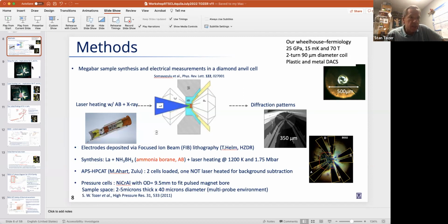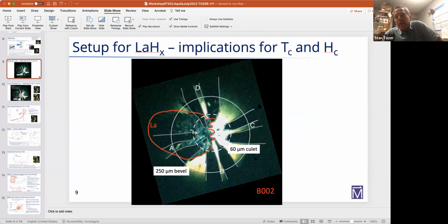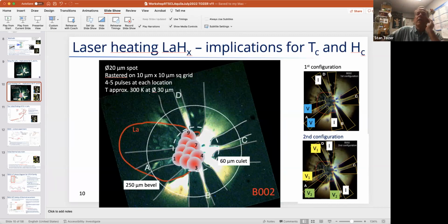Okay, so now again we're back to that micrograph of the sample. You can see the lanthanum. It just touches the two electrodes here and here, so we're able to do a couple permutations of current and voltage, and all of them show the same result, but at different amplitudes. Okay, and then as far as the laser heating, Friedemann realized that it might be best to defocus his laser beam, and he did that. He defocused to about a 20 micron spot.